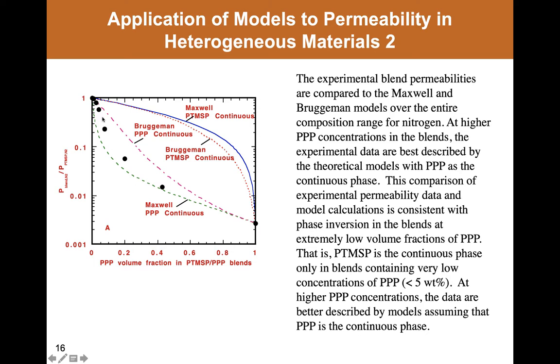If you look over a broader composition range all the way out to pure polyphenyl propyne, what you find is that the data are much better represented by a model which assumes that the polyphenylpropyne is actually the continuous phase rather than the PTMSP, despite the fact that at low compositions on the left-hand side of this graph, at low compositions of polyphenylpropyne, this material is mainly PTMSP. And this brings about another concept in the transport in heterophase or heterogeneous materials, and that is the fact that one component or the other may be the continuous phase.